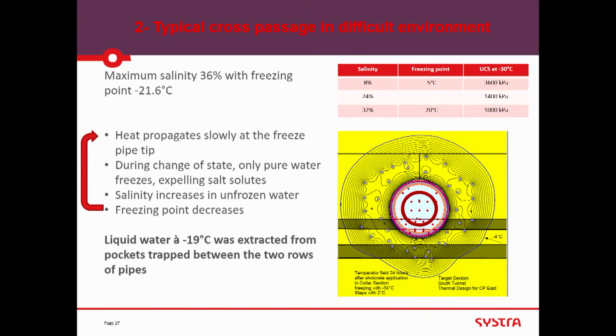So the effect of salinity is quite important. Seawater has about 30 grams per liter of salt, so it's 3%. Okay? Where we were, we had a little bit more than 30 grams per liter. So for 8% of salinity, the freezing point is -5, which was our project. And under -30 degrees, in fact, UCS is 3.6 MPa. But if you have a salinity of 32%, the freezing point is -20, and the UCS is 1 MPa compared to 3.5 MPa. So you see that at some point, if you get too much salt in water, it's a little bit difficult.